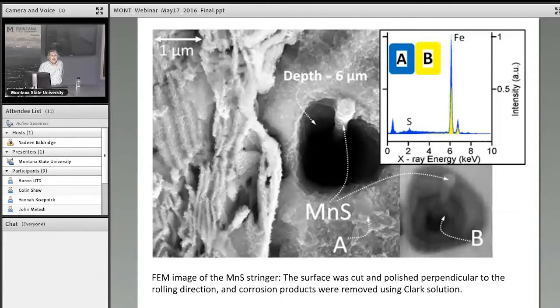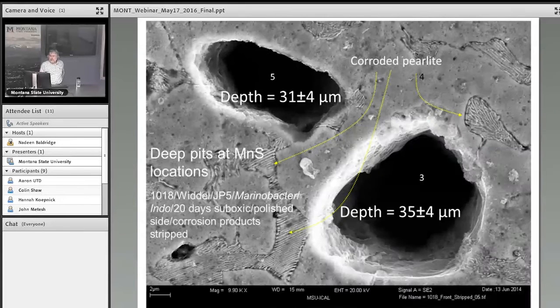Here, for 6 micron, maybe it's not impressive, but look at that. These are similar; you just wait a bit longer, and wherever there was manganese sulfide, you have deep pits evolving. Essentially, they will coalesce together and make bigger pits. But the point is that this is at 35 micron. Try to measure this with any other technique that you can tell me. I'll bet my best shoes that nobody can measure this. This is how we do it.